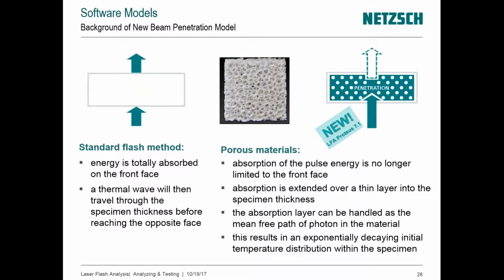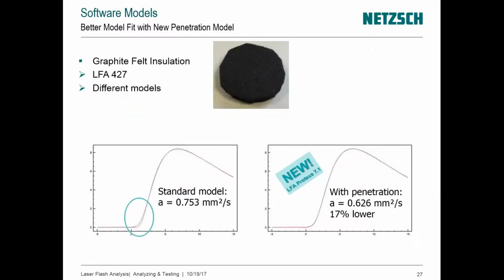Again, if I can summarize a little bit, the reason why we call it beam penetration is that because of the voids on the surface, the energy will not only be absorbed on the front surface, it will actually be absorbed at the bottoms of the voids too, whatever void is exposed to the pulse of energy. Very important to account for that. Just to show you how the signal will look if there were penetration or not, or how the model accounts for this penetration, for this porosity.